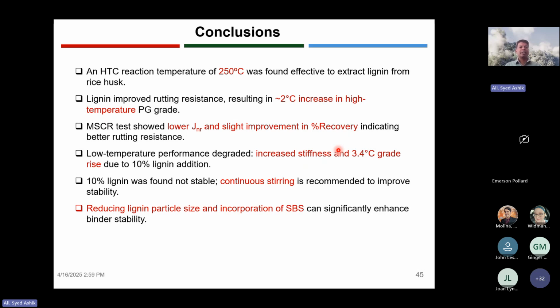We have found that the HTC process can be used at a 250 degrees Celsius temperature to extract lignin efficiently. And then we can use it for modification of our binder and use it in our asphalt mix or asphalt pavement. Lignin improved the rutting resistance, resulting in an around 2 degrees Celsius increase in the high temperature performance grade.